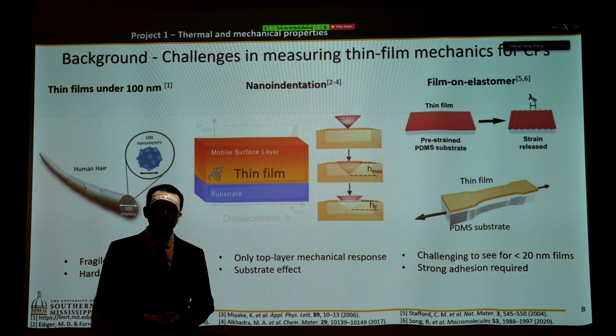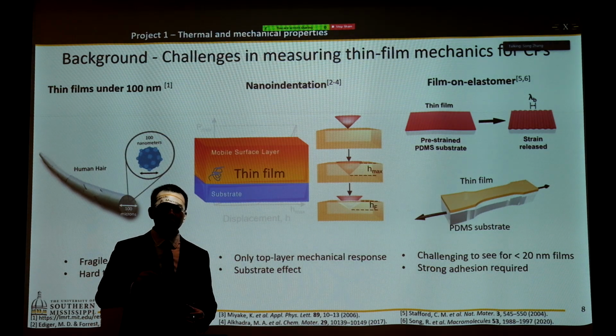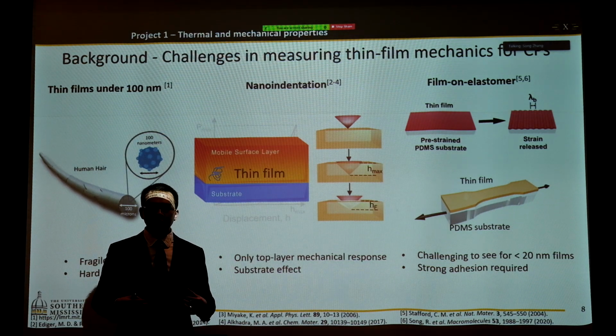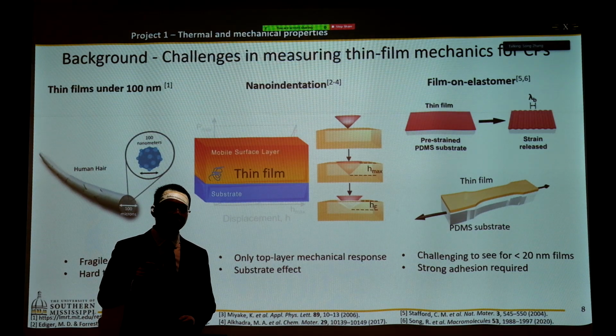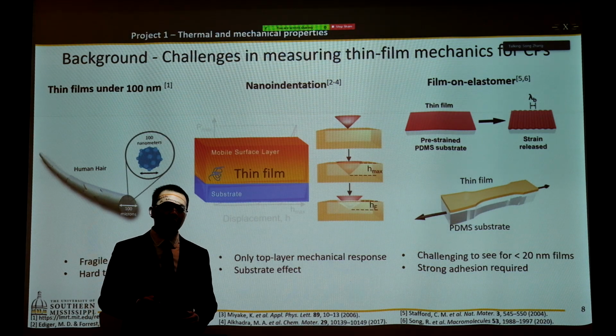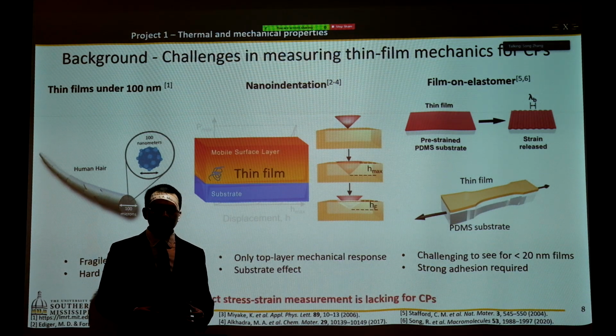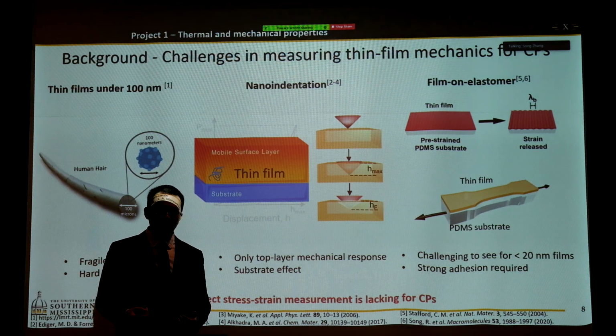since these thin films tend to be very transparent. Another challenge is that you tend to need a strong binding force between the thin film and elastomer to avoid delamination. However, that interaction could significantly affect the thin film mechanical and thermal response. That's why what we really need is a direct and quantitative measurement of stress-strain behavior for conjugated polymer thin films.